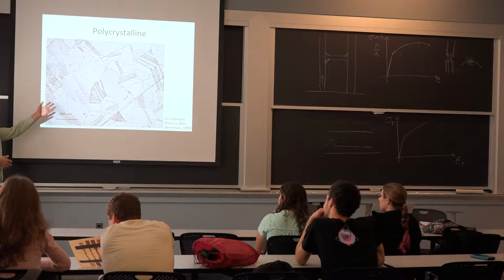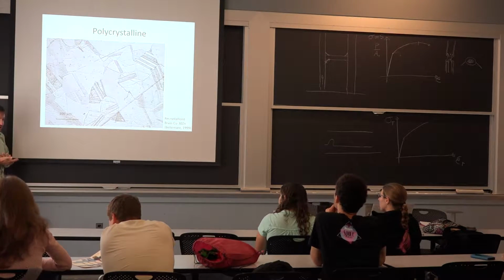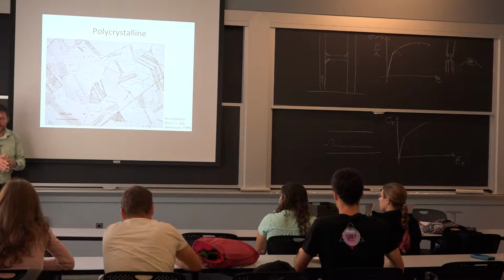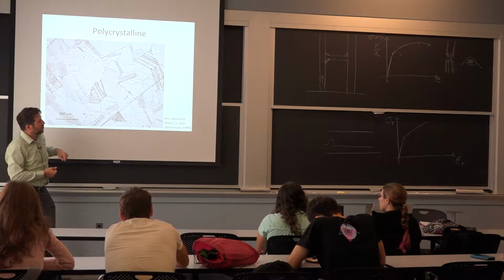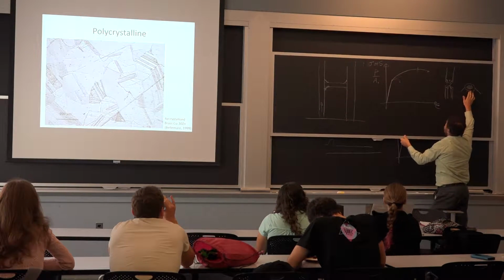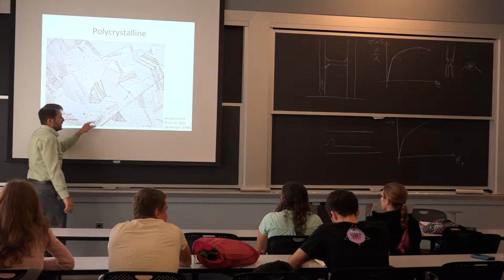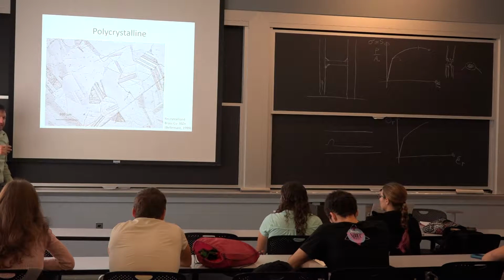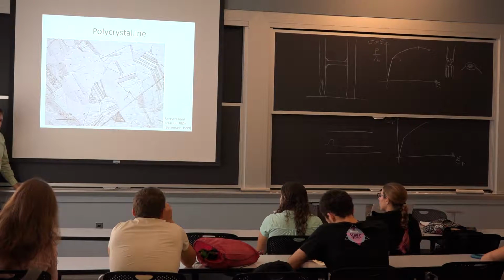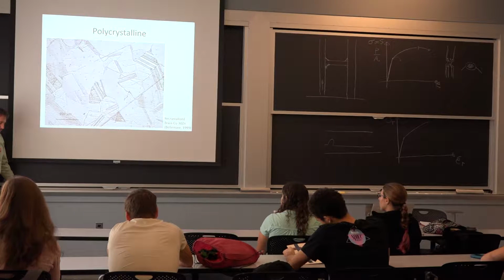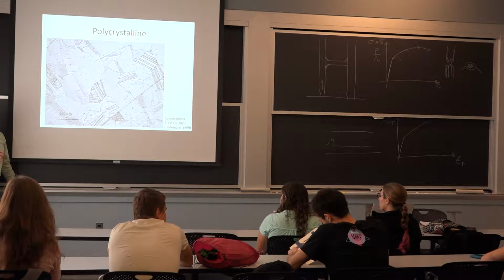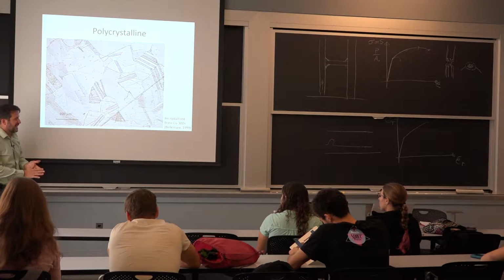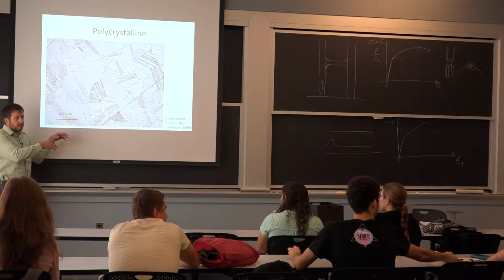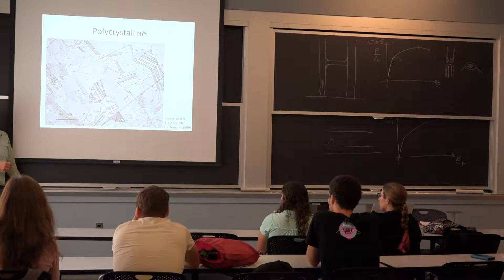When you see this, you're like, oh, wow, maybe this is going to break right there, right? Generally not. It's not because you have grain boundaries that when I deform and start forming the microvoids, what we were talking about over here, there's nothing to say that the voids are going to start forming at the grain boundary. So you don't have to worry about that in the general case. If there is an effect of the environment, and I can't go too deep into that, say a high hydrogen environment, something that is very corrosive, you can have a situation where these small atoms are going to go into the grain boundary preferentially and cause different kinds of failures. So it is possible, but in general, especially in our context of forming material here, we don't want to consider that a problem.